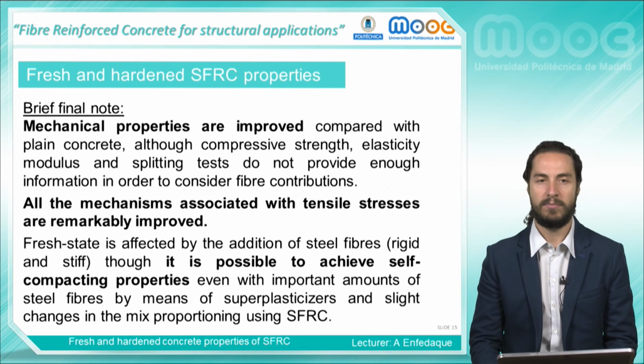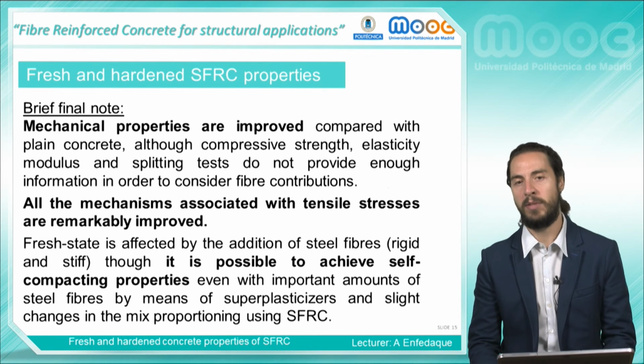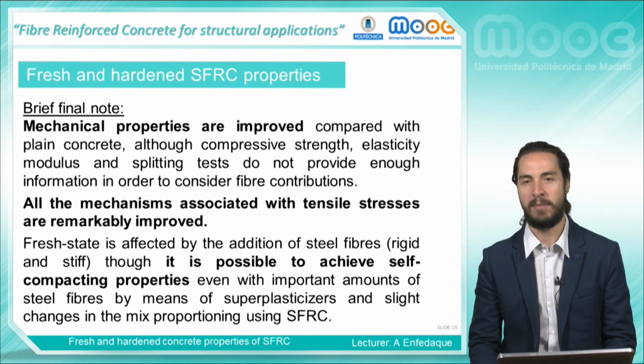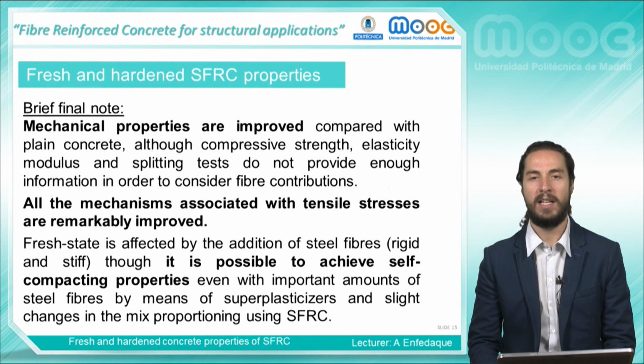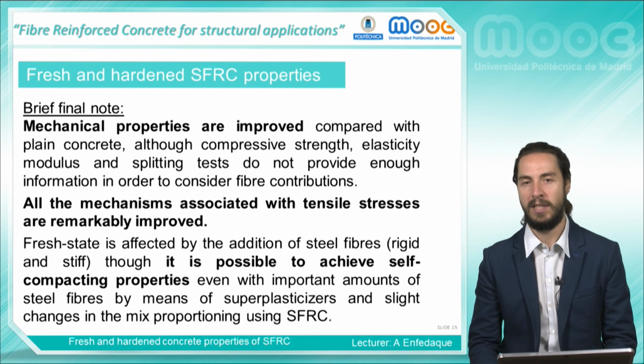In conclusion, mechanical properties are improved compared with those of plain concrete, although compressive strength, elasticity modulus, and splitting test do not provide enough information in order to consider fiber contributions. All the mechanisms associated with the tensile stress are remarkably improved. That is why fracture tests are needed in order to evaluate the contribution of the fibers in structural design.